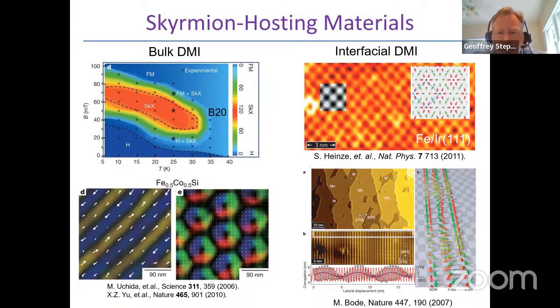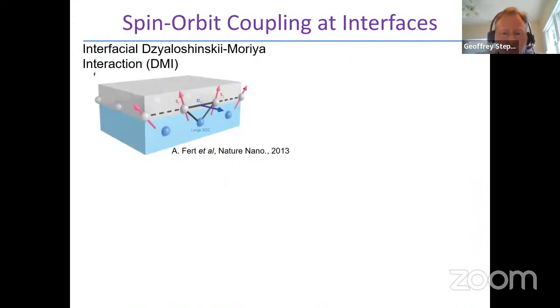The other place where one finds a broken inversion symmetry naturally is at interfaces or surfaces. And in appropriate materials, at an interface or surface, there can be a strong interfacial Dzyaloshinskii-Moriya interaction that likewise can generate non-uniform spin textures, so spin spirals or magnetic skyrmions. And in fact, such textures, particularly skyrmions, have been seen to be very small under conditions, at least at very low temperature, down to atomic scale by spin polarized STM. Initial observations in thin films or at surfaces were only at low temperature, and only in rather difficult to prepare single crystal or epitaxial films.